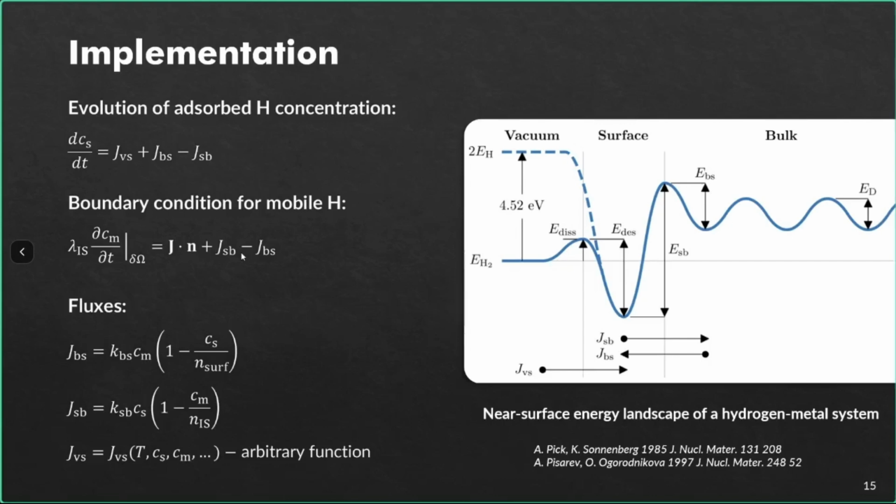And to make this model flexible, we implemented an arbitrary function that defines all possible surface mechanisms that determine desorption and adsorption, and rely on the temperature and concentration of hydrogen. The implemented model was verified and validated.